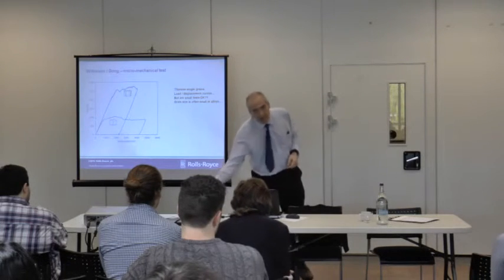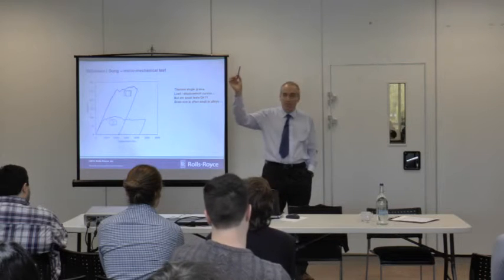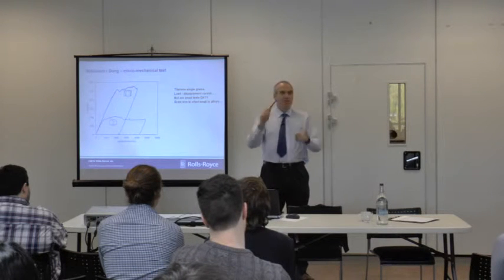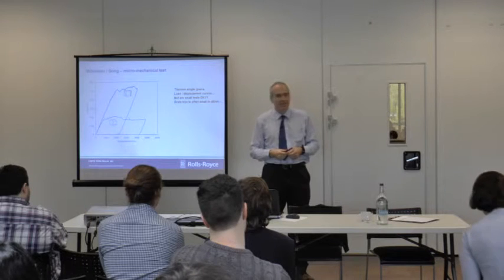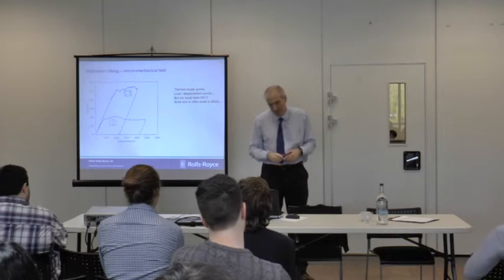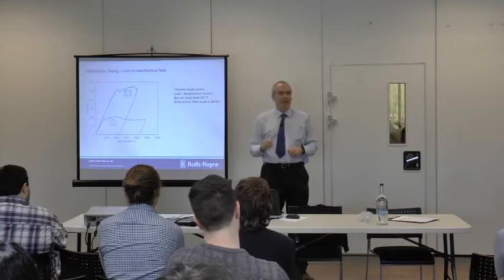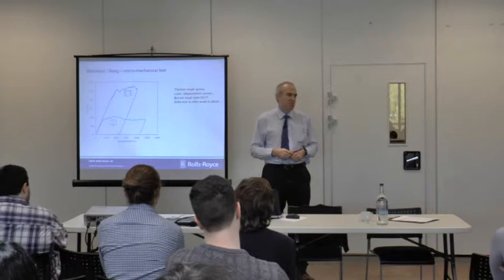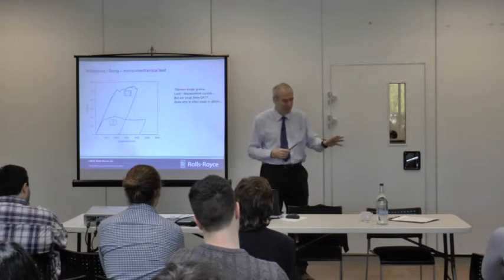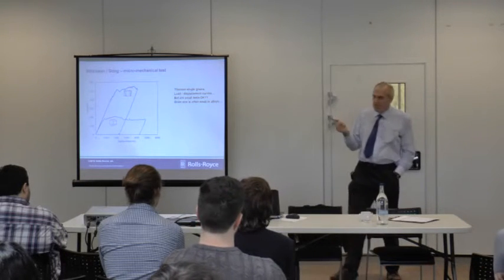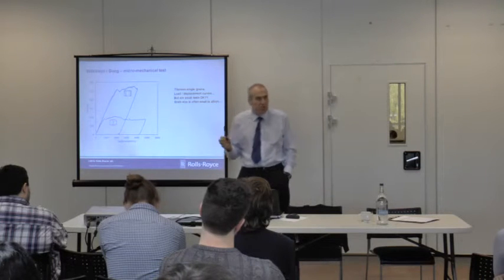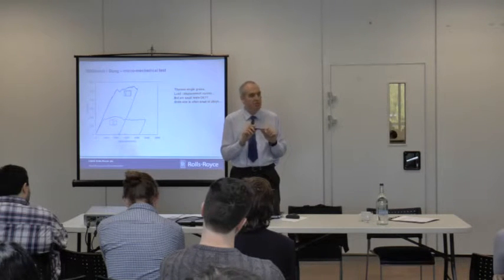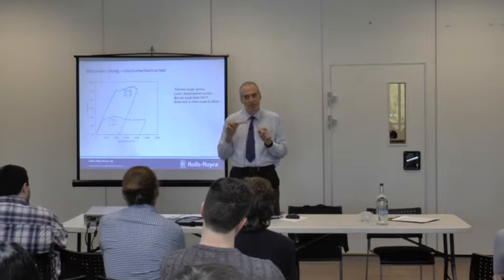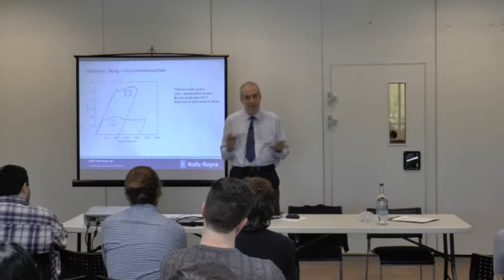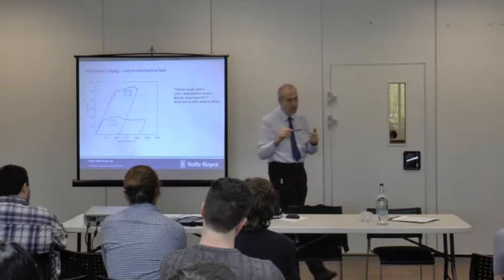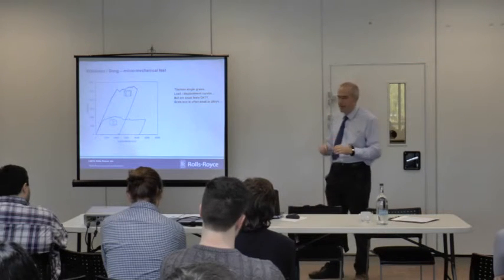So if I took a single crystal, and I bent it and got a strength of X, you kind of go, well, okay, very interesting, Dave, go away and do something useful. So I make it smaller and do it again. I halve the size and do it again. I get pretty much the same answer. It's like, okay, Dave, you're really boring me now. Once I get down to typically about 2 or 3 microns, I suddenly find that the strength of the material starts to go up dramatically. So, single crystal, no jiggery-pokery, length scale strengthening to do with how dislocations interact with one another when you've got a plastic strain gradient.